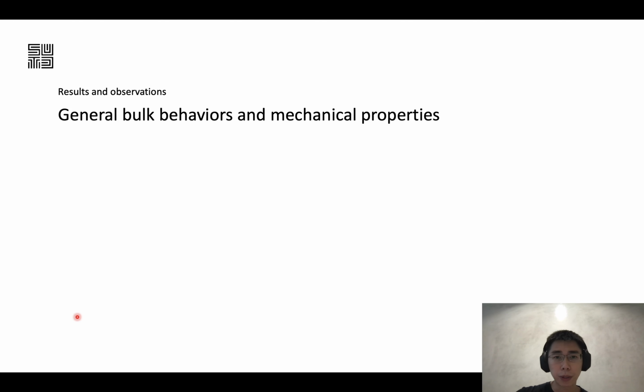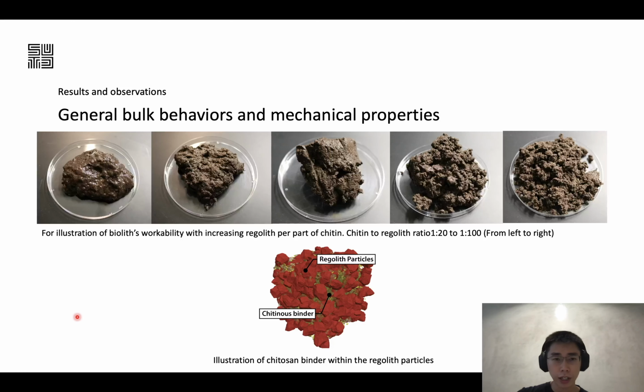First off, the general bulk behaviors and mechanical properties of the composite. Now in its wet form, as we add more chitosan, we can see that the workability of the mixture changes. On the extreme left-hand side is where we have a lot of chitosan solution and very little regolith, and on the extreme right-hand side, a lot of regolith and very little chitosan. We see that the workability changes between the two extremes of being non-palatable and being very friable, which is very clumsy. The illustration at the bottom is just to depict how the regolith particles are dispersed in the chitin matrix.